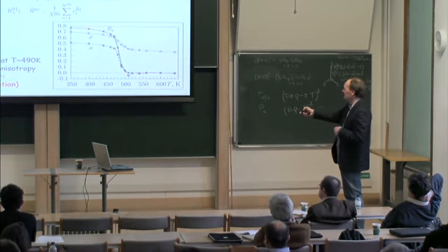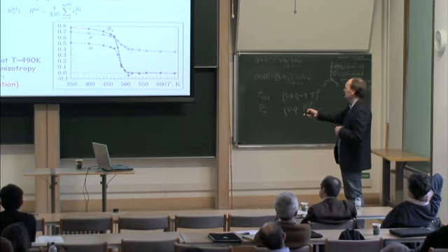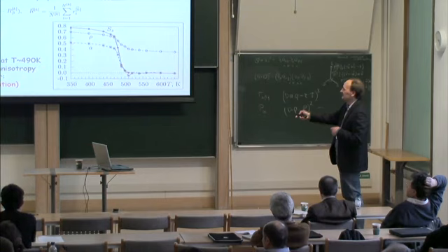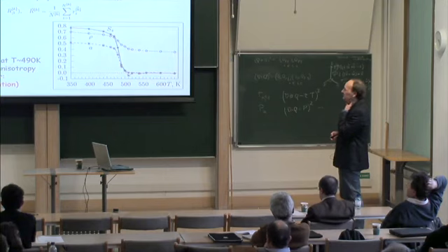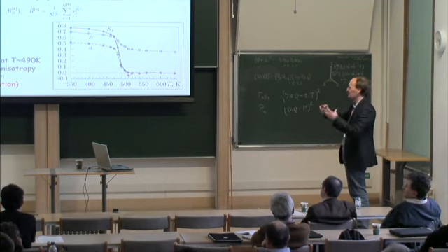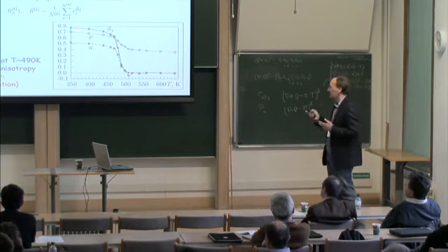And what we have here is the symmetric nematic order parameter going to 0 at 500 degrees. And also the same is the asphericity of the molecules, absolutely following the same route, where asphericity is evaluated as some combination of the components of the gyration tensor. So we have absolutely perfect correlation between the shape of the molecule and the phase.